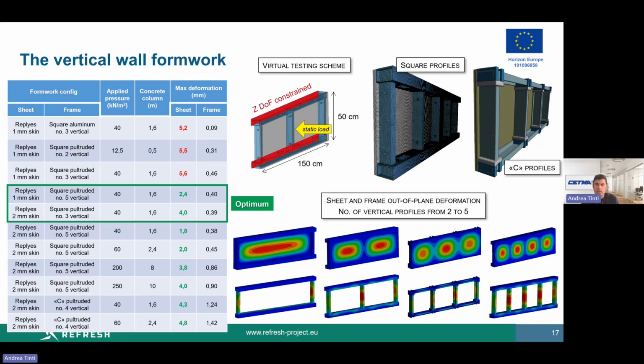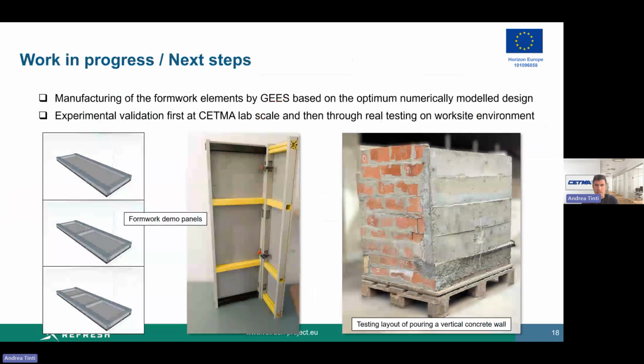Then, to model the process of concrete pouring, a static pressure was applied normally, corresponding to a fresh concrete column of variable height, and the out-of-plane deformation was numerically measured, mostly affecting the sheet rather than the rigid frame, which always resulted quite unaffected. So in the end, virtual testing allowed us to optimize the constructive parameters to get the required performance, basically the permitted pressure and deformation.